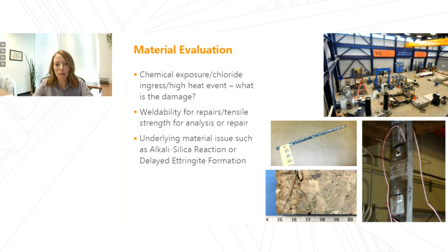When we talk about reinforced concrete issues that might have an underlying material issue, such as DEF or ASR, we really want to know, okay, what is the extent of what we're talking about? Is it a superficial issue, or does it have the potential to substantially affect the structure? And the only way we can tell that is from a material evaluation. It's not enough to just do a visual assessment and know that you have cracks if we don't really understand what's causing the cracks and what the potential there is.